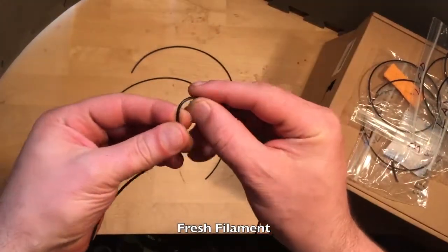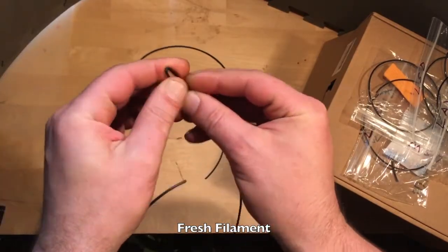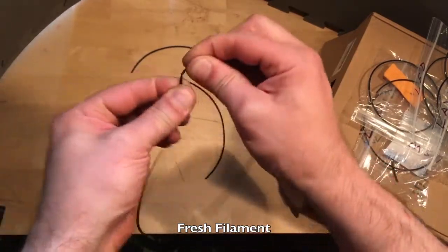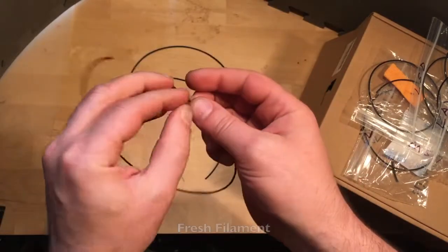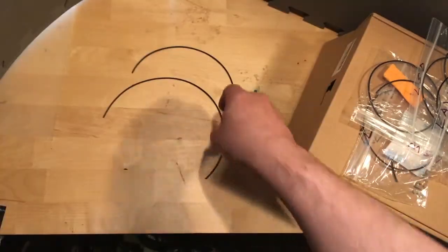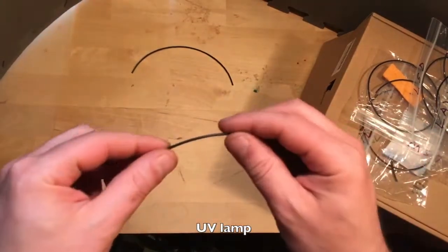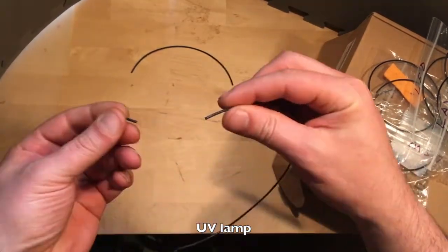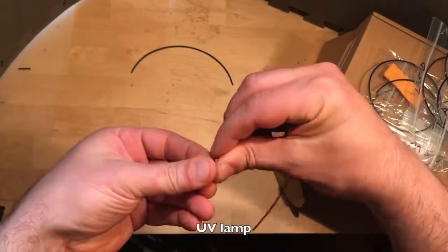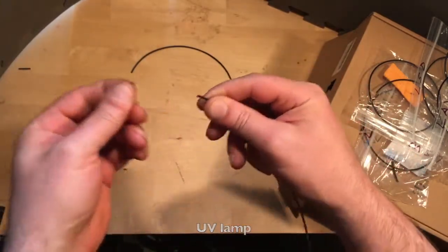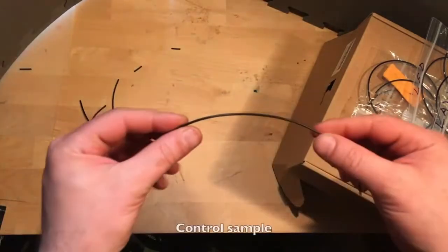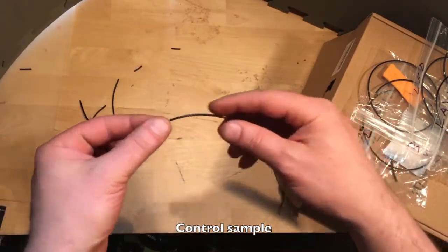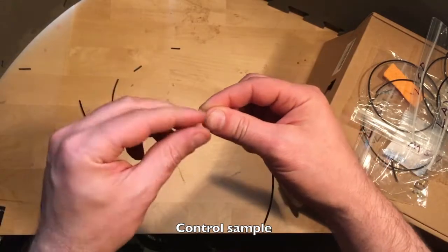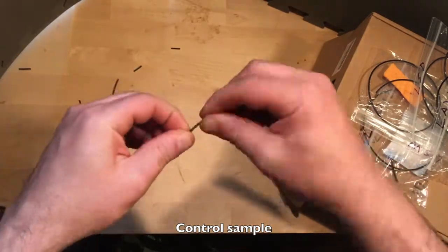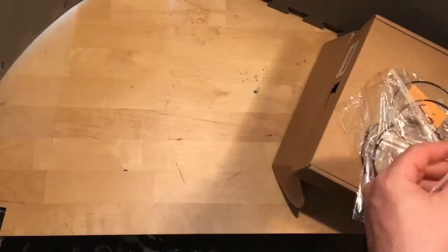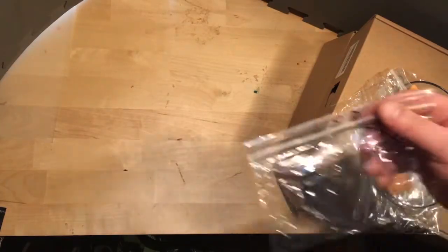So here as a control, this is right off the reel. You can see it's very pliable, it doesn't snap, and it just kind of becomes gummy and chewy when I try to break it, and that's not coming apart. Now let's look at these 2 other samples. This one right here was snipped off the reel last night and then put under ultraviolet light for the night. Now as you can see, that's just practically falling apart in my hands. And this was one of the control samples. It was just sitting on my bench right next to the printer the entire time. And as you can see, that's also extremely brittle and just falling apart in my hands as well. And that establishes a pretty good baseline for the rest of the tests.